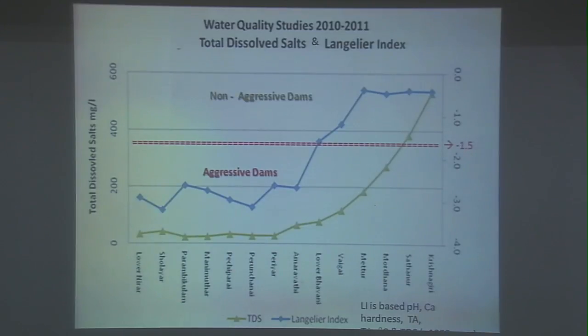And of course, we have plotted the TDS of 14 dams and LI of 14 dams. We are trying to establish that there is a definite relationship between the TDS value and the LI. We are trying to arrive at a thumb rule based on which the field people can conclude whether our dam has aggressive water or not. You can see that TDS is directly proportional to the LI. If the value of the LI is above minus 1.5, it will come under the category of non-aggressive dams.